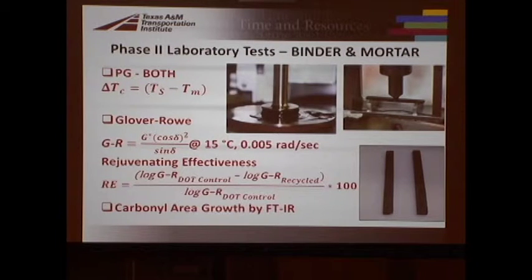We're also using another parameter quite frequently that's gained some recent attention, called the Glover-Rowe parameter. The Glover-Rowe parameter is just a different combination of G* and phase angle. Instead of G* over sine delta or G* times sine delta, it's G* times the cosine of delta squared divided by sine delta. So it's just a different combination of G* and delta that you would get out of the DSR. However, it's an intermediate temperature property. It's at 15 C, and at a set frequency of 0.005 radians per second.